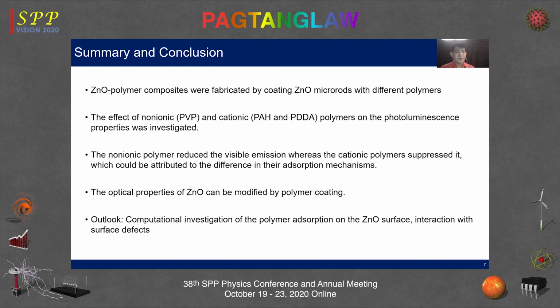And for the summary and conclusion, the ZnO polymer composites were fabricated by coating ZnO microrods with different polymers. The effect of non-ionic PVP and cationic PAH and PDDA polymers on the photoluminescence properties was investigated. The non-ionic polymer, PVP, reduced the visible emission, whereas the cationic polymers, PAH and PDDA, suppressed it, which could be attributed to the difference in their adsorption mechanism. And the optical properties of ZnO can also be modified by polymer coating. And for an outlook, a computational investigation of the polymer adsorption on the ZnO surface or interaction with the surface defects.